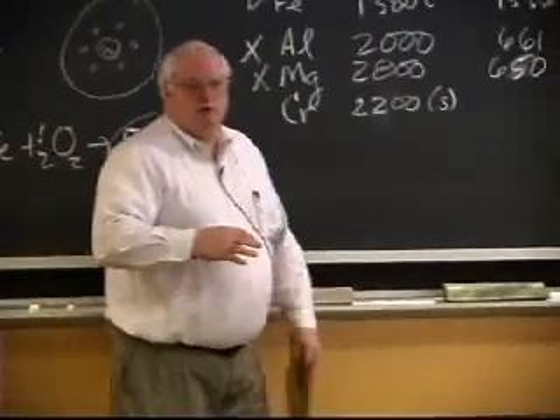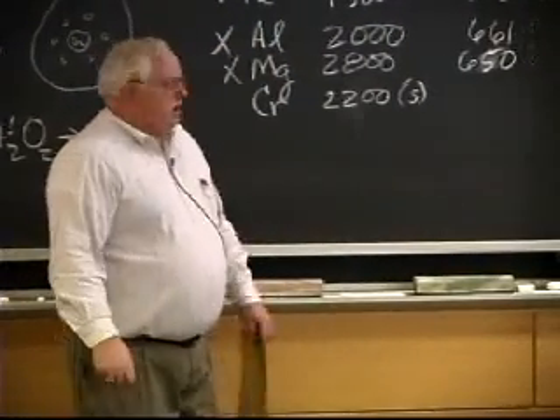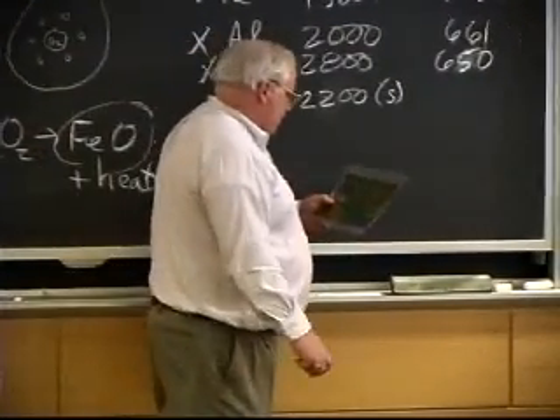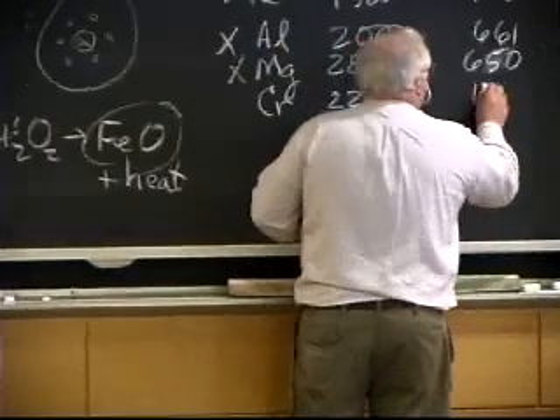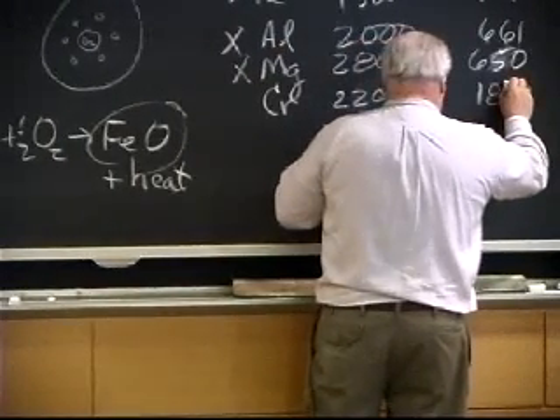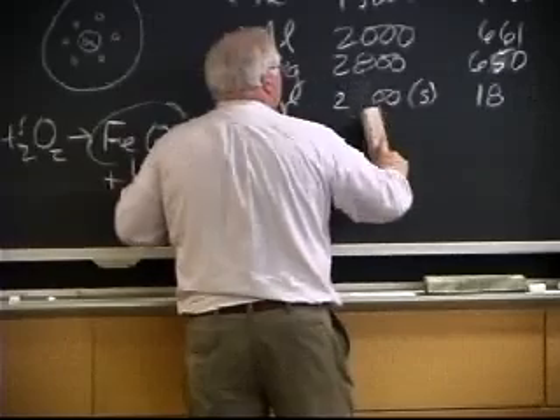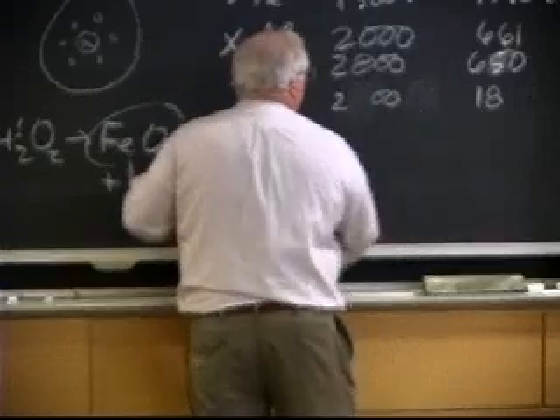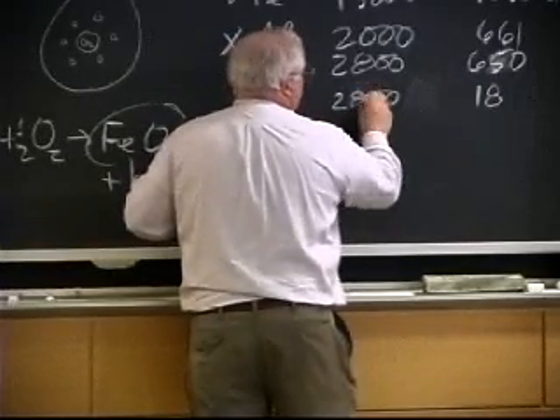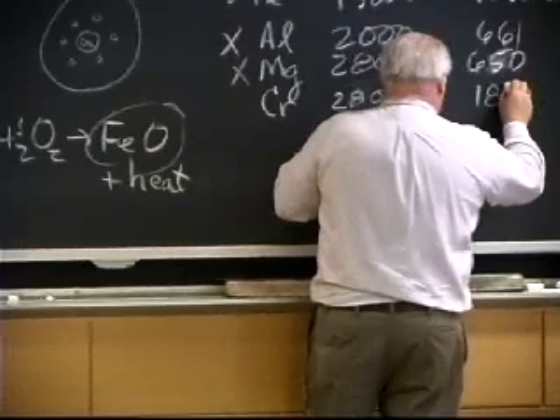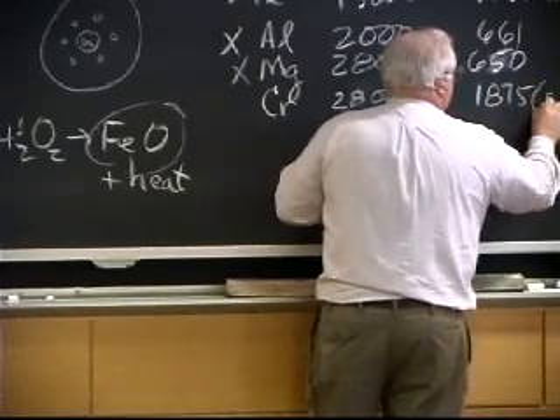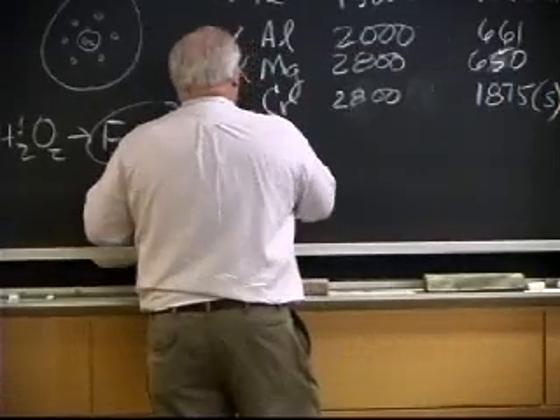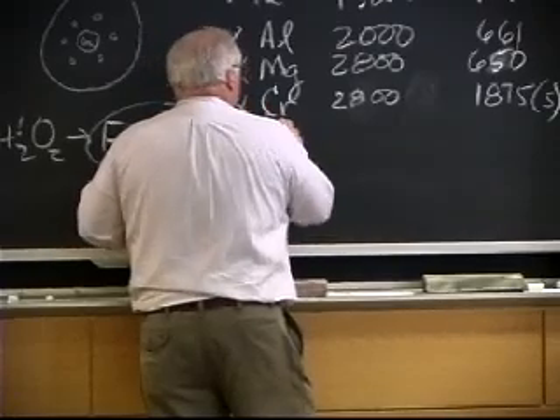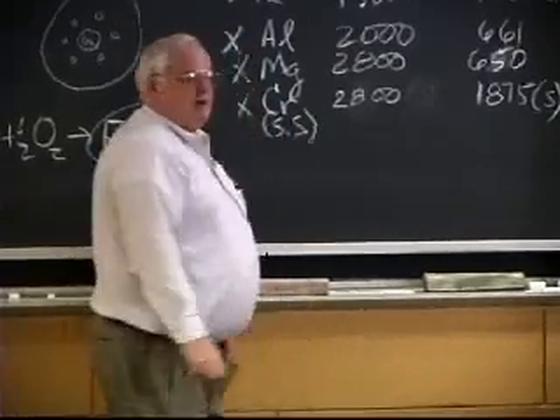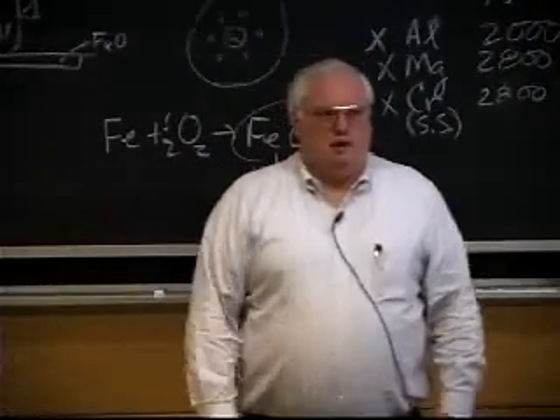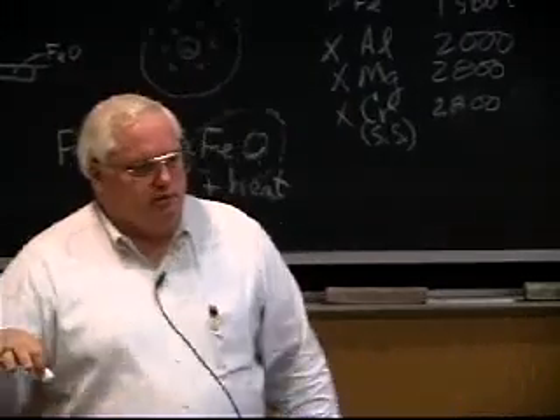Chromium, as you heat up, the solid just starts to vaporize away. You don't get chromium liquid unless you go to high pressures. Turns out, oh, I'm sorry, that was right. There's 2800 for the chromium oxide. It's 1875 for the metal, which sublimes. And so that means that stainless steel cannot be flame cut because it has a chrome oxide layer on the surface.